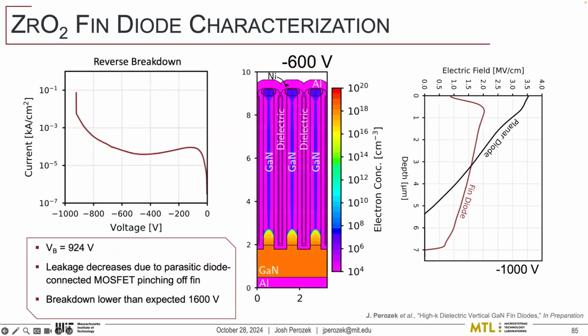And the most interesting behavior of these is actually in our reverse breakdown characteristics. So as you deplete this, normally you'd expect for any diode that your leakage current just increases continuously. But for these devices, you actually see that it dips down in the middle. And it's very strange behavior for any sort of diode. And the reason we believe this is happening is because these diodes kind of act like a diode-tied reverse biased MOSFET.